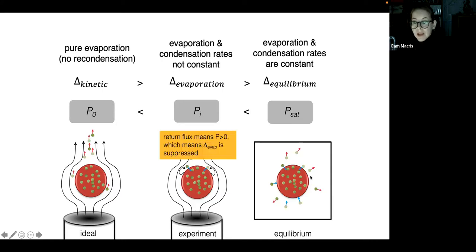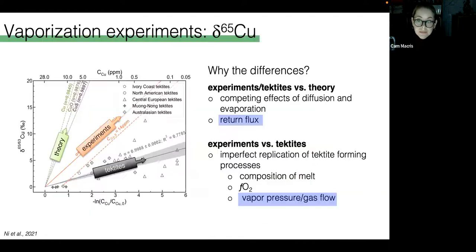And the fact that we have some return flux in our experiments means that the partial pressure is greater than 0, and thus the fractionation will be suppressed relative to the purely kinetic case. So if we revisit this figure now, I think we can be more convinced that the return flux and the partial pressure at the surface of the melt are likely playing a role in these differences. The way that the gas is interacting with the melt is having an effect on the isotope fractionation here.